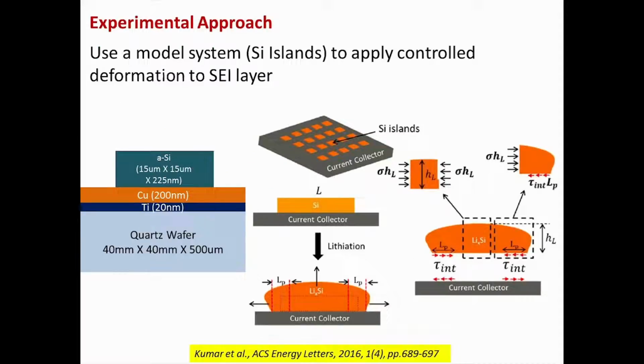So I would like to first talk about the experimental approach that we need to use to answer part of these questions. If we are talking about the mechanics of the SEI layer, we need to use a model system so that we can apply a controlled strain to the SEI layer. And for that, what we have come up with is a patterned silicon island structure. The sample geometry is a quartz wafer, with the current collector, a titanium and copper layer, on top of that, and silicon islands fabricated through a photolithography process.